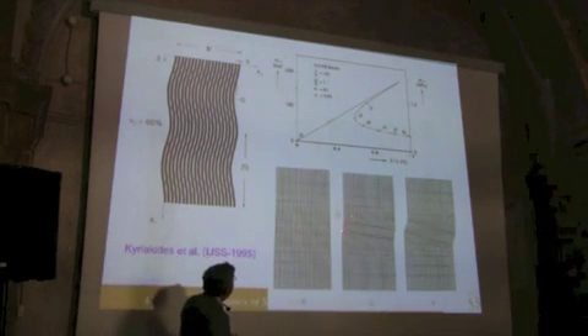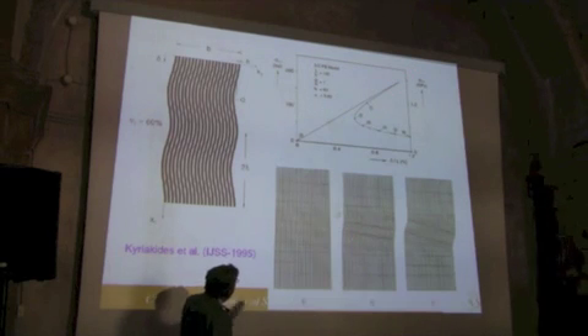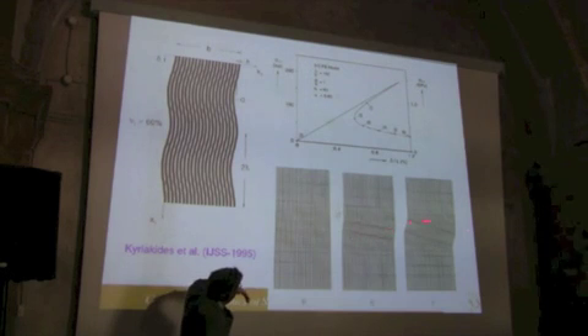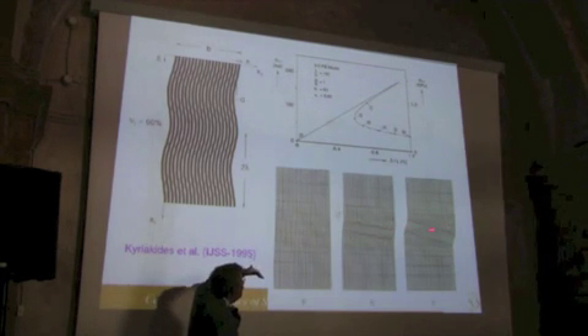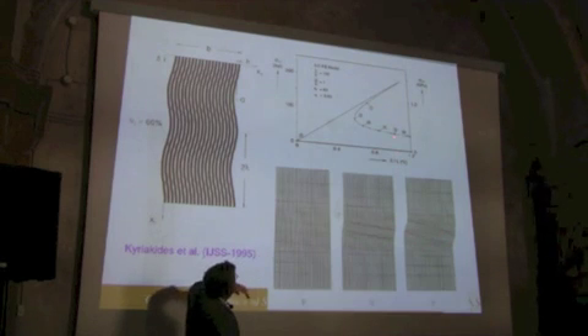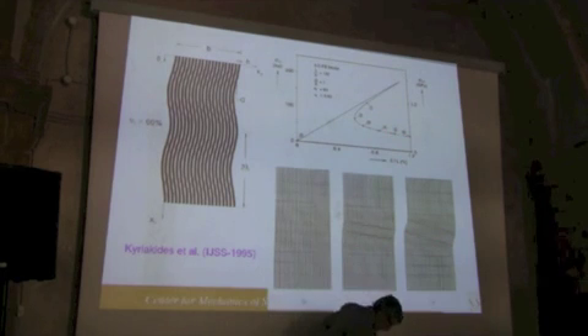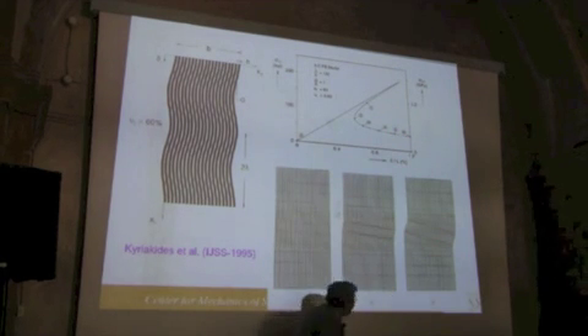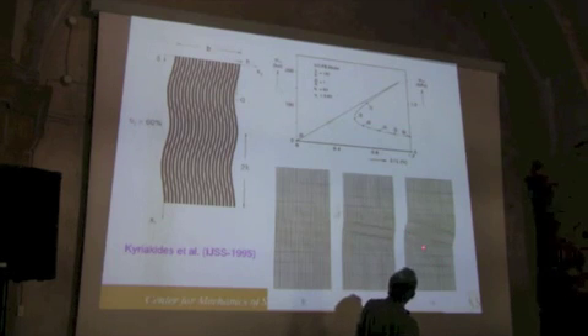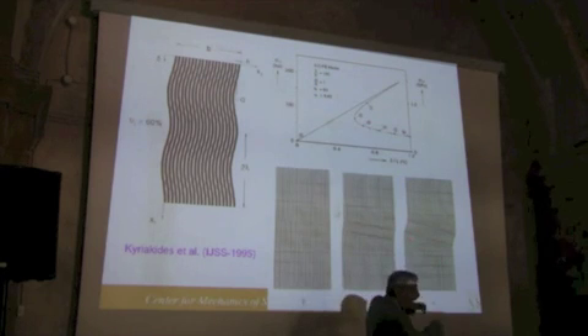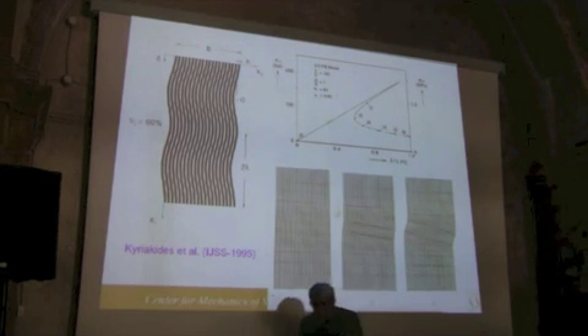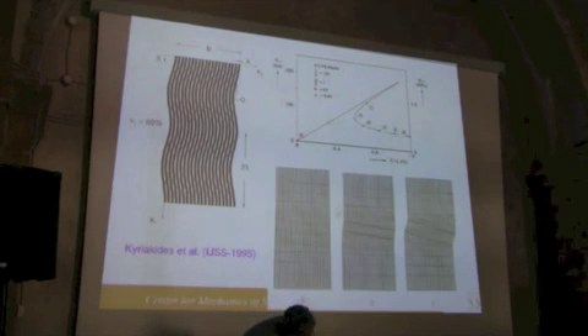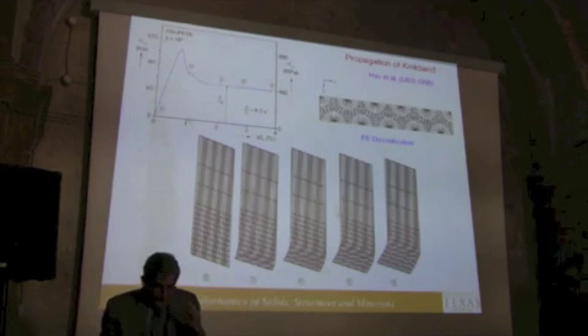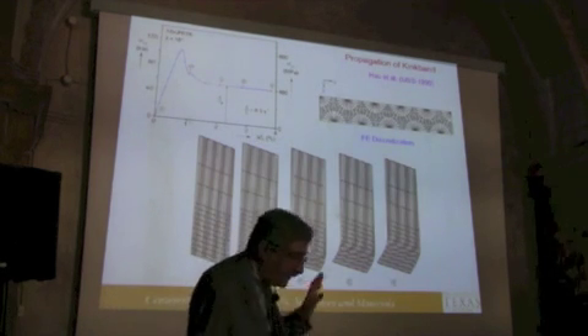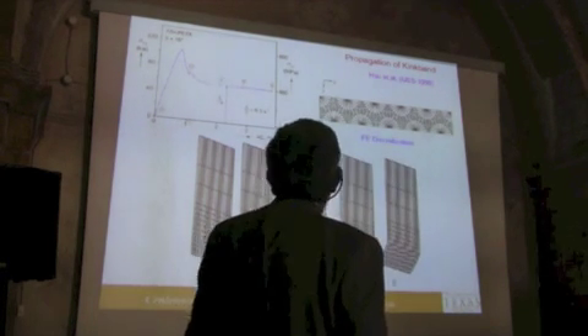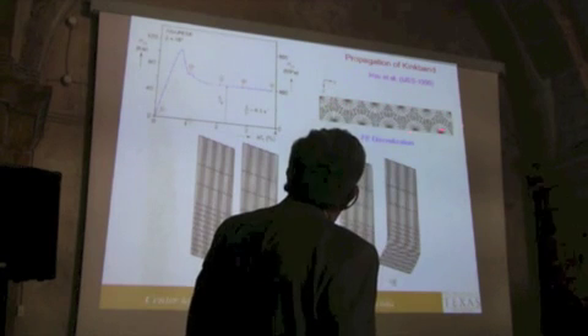But you see what happens to the fibers. Okay? They are bending. When we reach here, they start bending. And this bending keeps rotating, okay? The band keeps rotating and develops as you see by the time I come here. And what happens is that when they bend sufficiently, they break. We don't have the breaking in this model. Okay. Now, if you want to see that propagation, and definitely this problem requires more work.